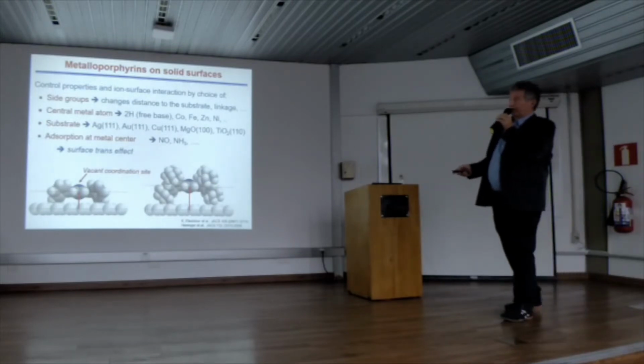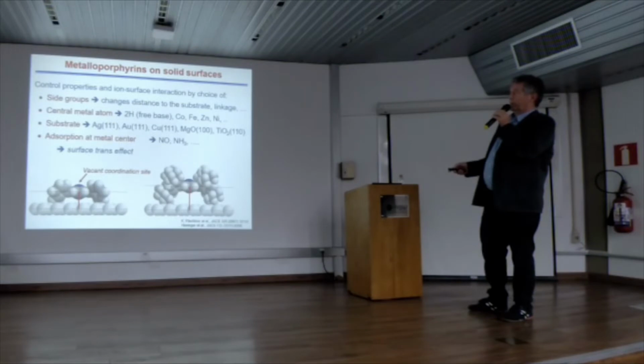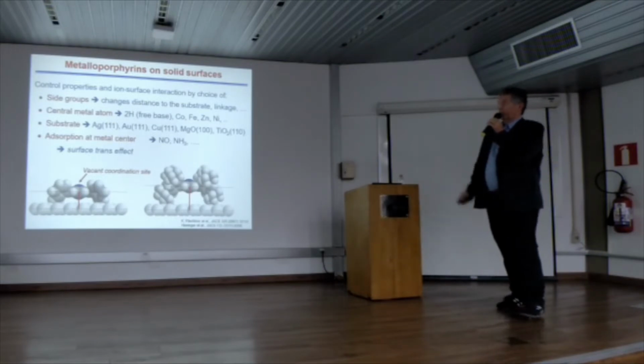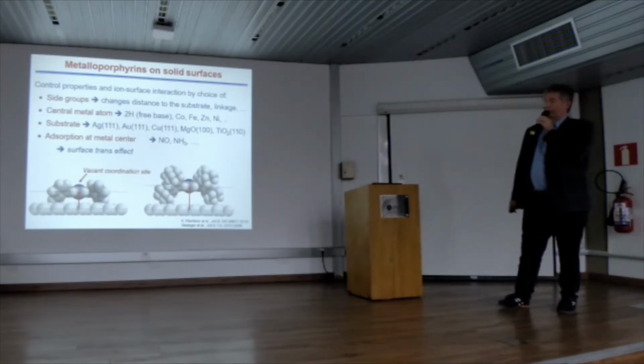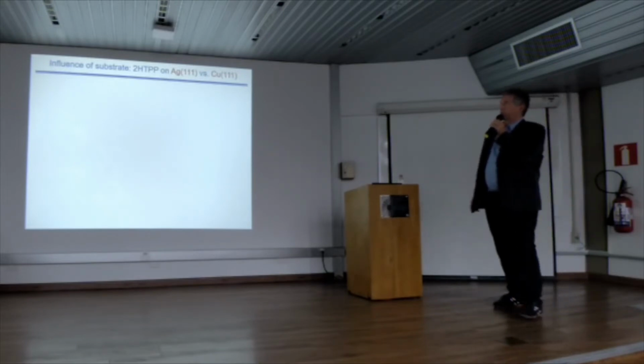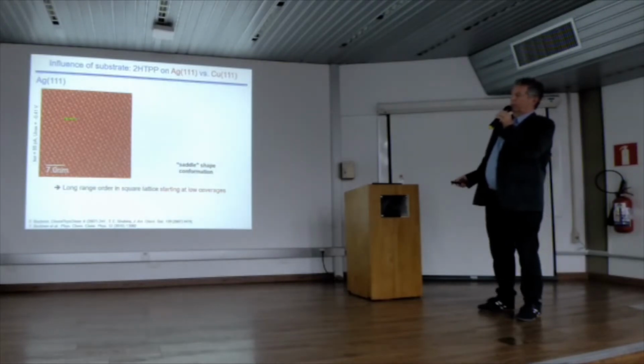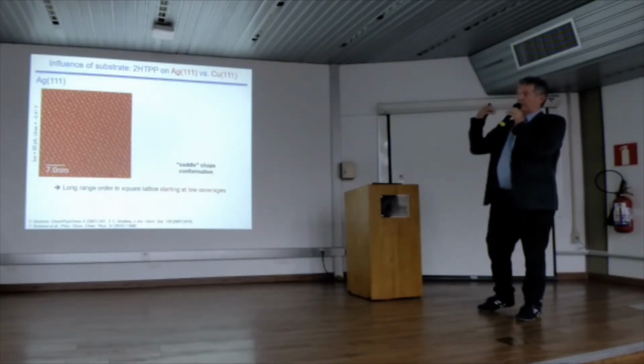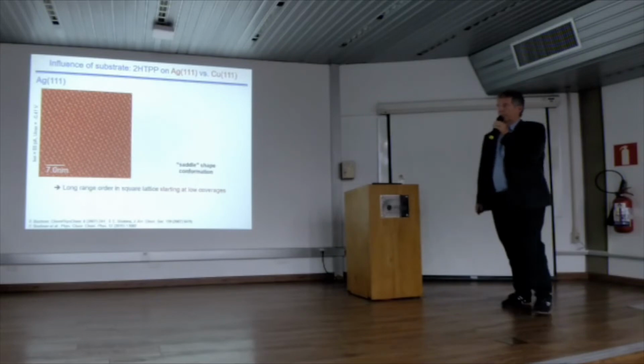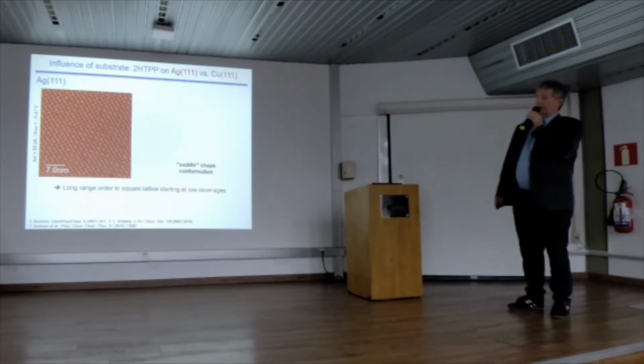And I start out with modifying the surface and seeing what different phenomena you can see. So we vary the substrate. It's a free base porphyrin here, so no metal atom in yet, on silver, on gold, and on copper. Okay, on silver, the system is very simple, nice. What you do is you have a surface, you deposit the porphyrins, you just evaporate them onto the surface in vacuum, and then you get the perfect two-dimensional structure.